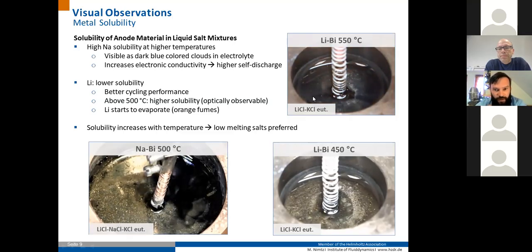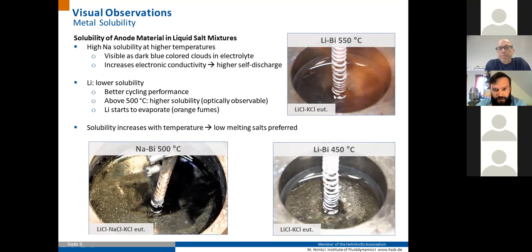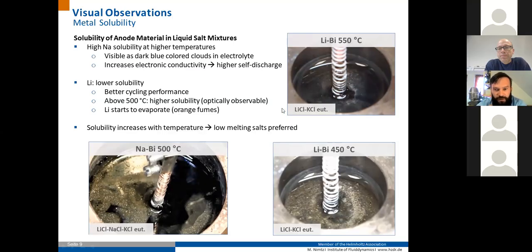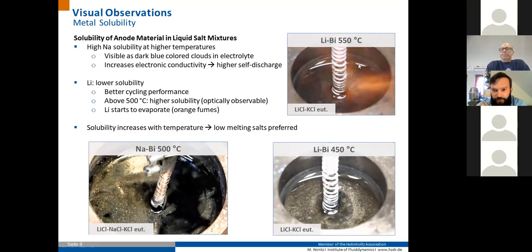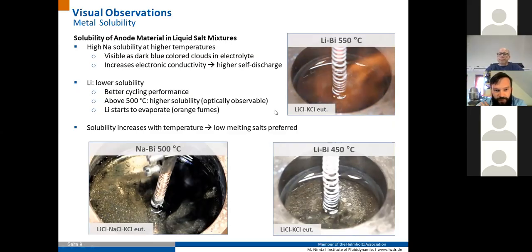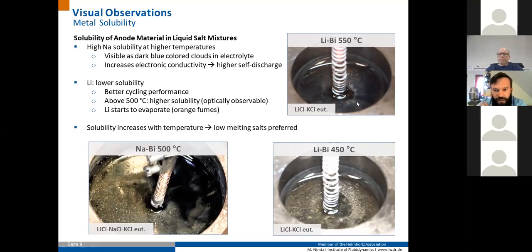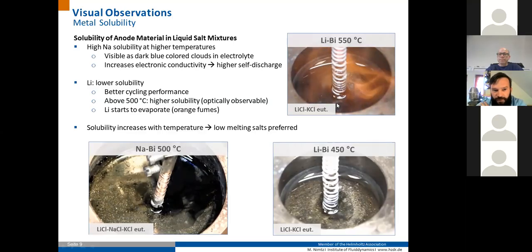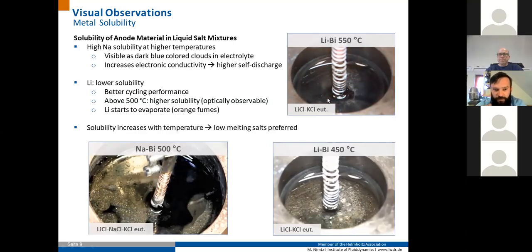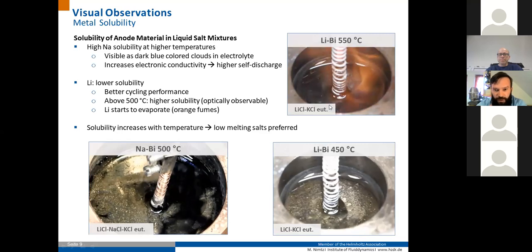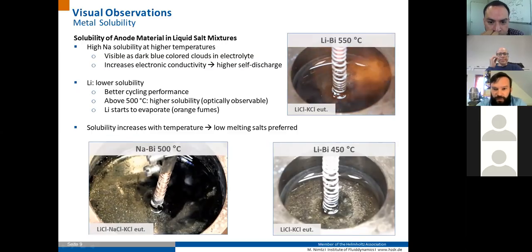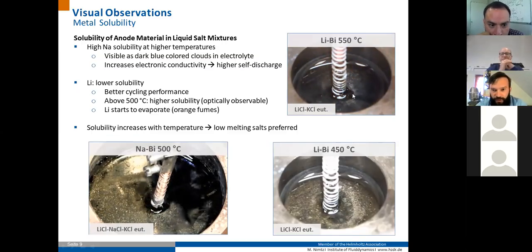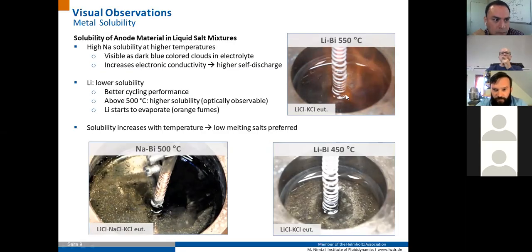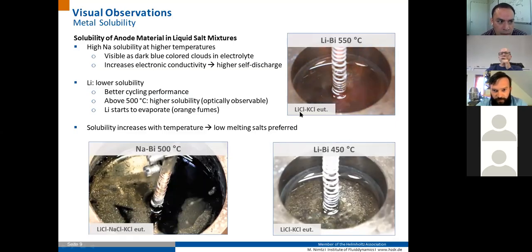The video on the upper right side shows some effects of evaporation of lithium at higher temperatures. Here you can see some orange fumes forming at temperatures above 500 degrees Celsius, 550 in this case. So it's better to stick to lower temperatures for experiments, because lower temperatures will have an effect on the solubility of the metal, which will be lower, and will also have an effect on the vapor pressure of the metal, which will lower the evaporation of metals, for example, lithium or potassium.